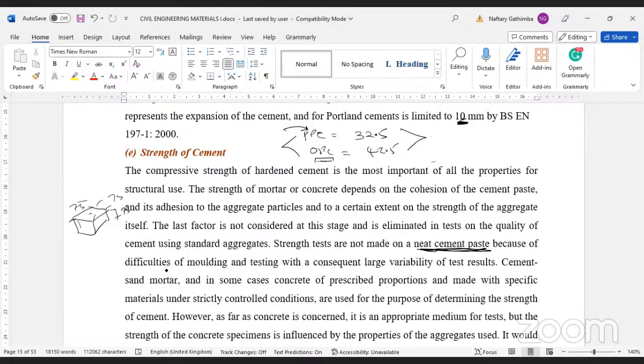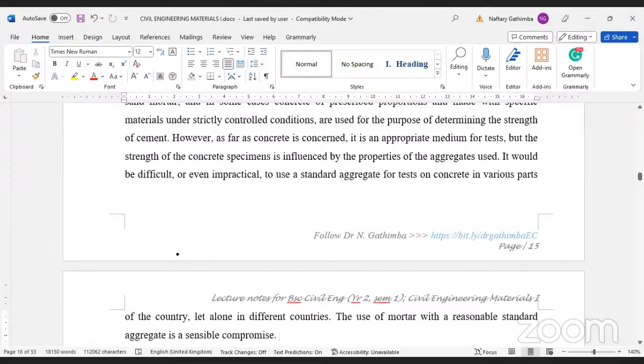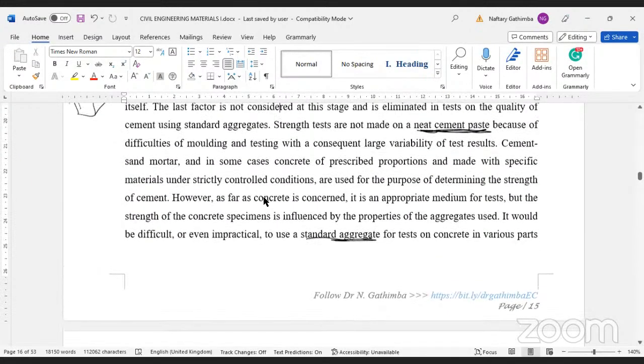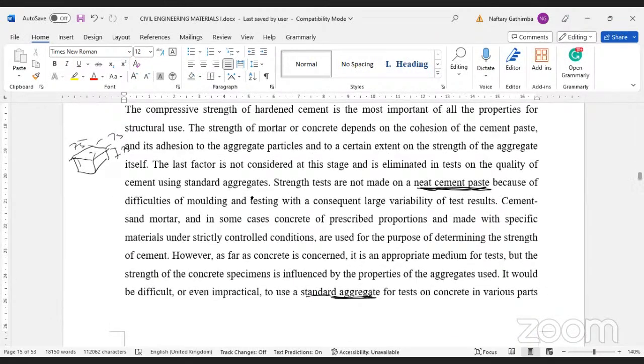A sand that is of known specific gravity or properties and so on. So we use standard aggregate or standard sand for us to be able to cast a mortar, and then we test the strength of the mortar instead of the strength of the neat cement. Because of that difficulty, there will be a lot of variation. So we take it to the compression machine you're going to see in the lab. You crush this to see what the strength, fc, is at 28 days. You check the strength.